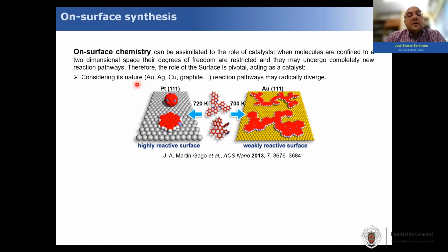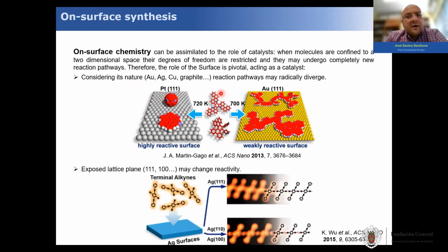So considering the nature of the surface, as you can see here, for these same two molecules, depending on whether you deposit them on top of platinum 111 or gold 111, you obtain completely different results. Well, not only the nature of the metal is important, but also the exposed lattice of the metal is quite important. As you can see in this example here, when you deposit these alkynes on top of a silver surface, it's not the same if the silver surface is a 111 lattice or a 110 or 100 lattice.